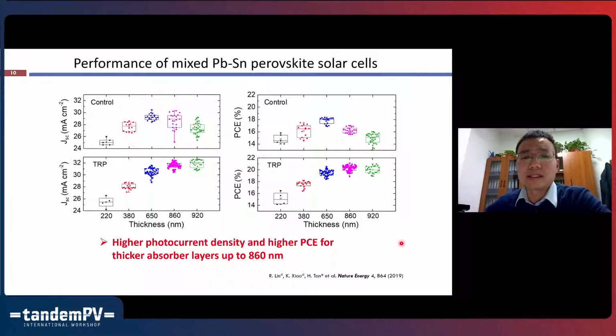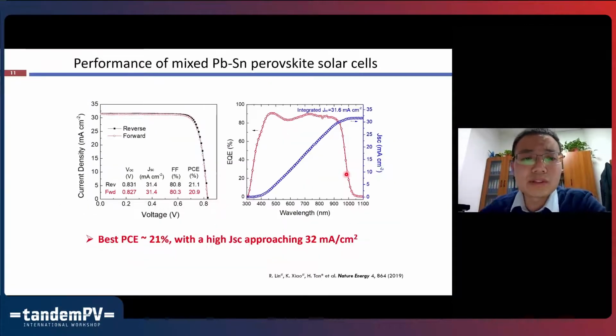Okay, yeah, thank you. Since we can use a multi-thick absorber layer, as we can see here, we can clearly see a big increase in the short circuit current density, and correspondingly, we can increase the efficiency of the narrow bandgap perovskite solar cells. After the device optimization, we can get the highest efficiency for narrow bandgap perovskite solar cells, for the first time close to 21%, and also from the EQE spectrum we can see that we get a very high short circuit current density that is almost approaching 32 milliamp per square centimeter.